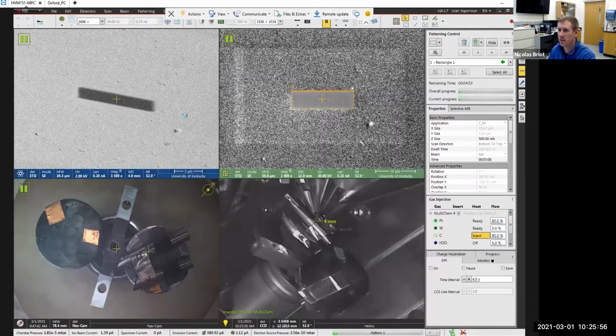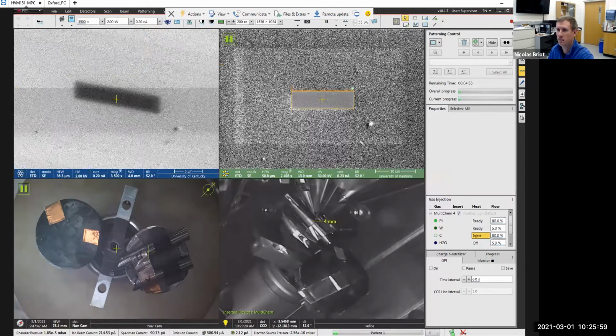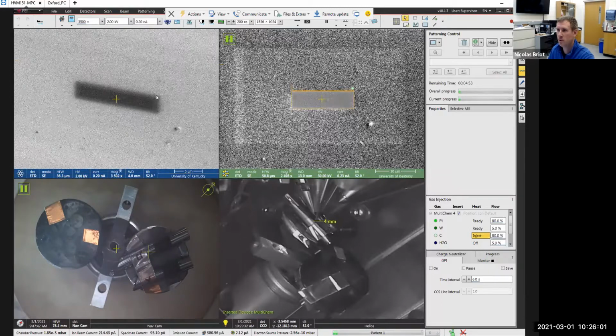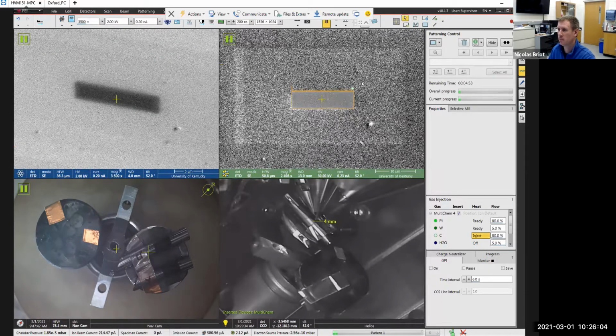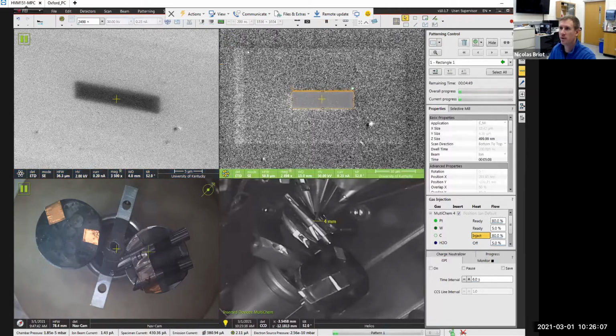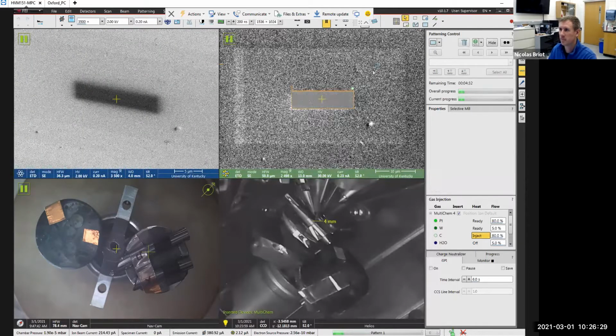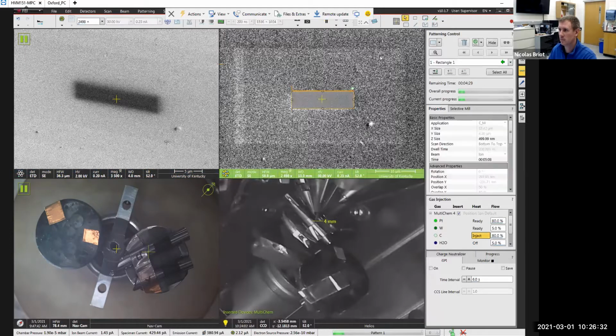Now I want to make sure I deposit okay. It looks like I am. So I'm going to keep going. You can already see where I did a few, not even seconds, but just a few frames with the ion beam. And then I changed the magnification, and now you can see the former magnification and how much it has impacted the original surface. It started milling things right away. So you've got to be careful when you use a focused ion beam, always. Check I'm doing the math right.